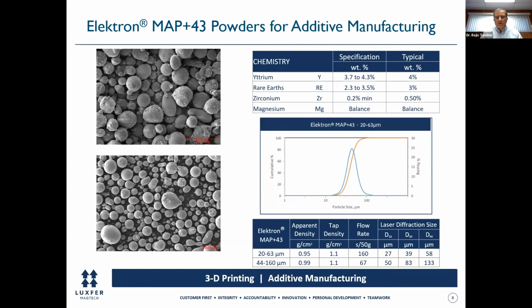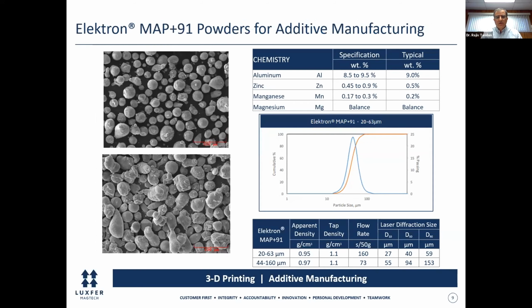So in terms of the powders available, this is one of the most common powders that we sell, the Elektron MAP+43 powder. It shows the spherical particle size and the key characteristics. These have been well demonstrated to flow very well on powder bed machines, the 20 to 63 micron powder. And again, like I said, custom cuts are available. And these have been well proven to perform well with a combination of high density and good mechanical properties.